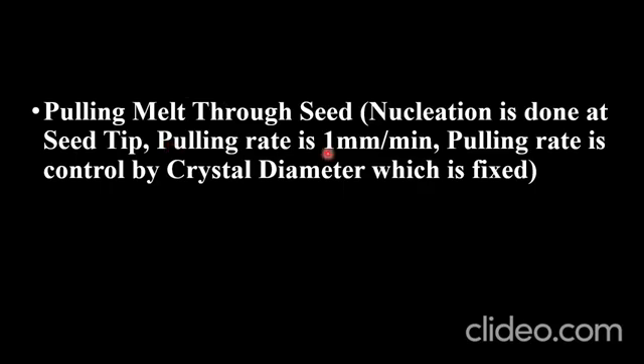Dear student, the pulling rate in the Czochralski technique is in the range of 1 millimeter per minute. We cannot increase the pulling rate because this can cause defects in the structure. So in industrial and commercial applications, it takes many months to produce a single crystal with higher diameter and higher length. The pulling rate is controlled by the crystal diameter, which is fixed in the conventional Czochralski setup.